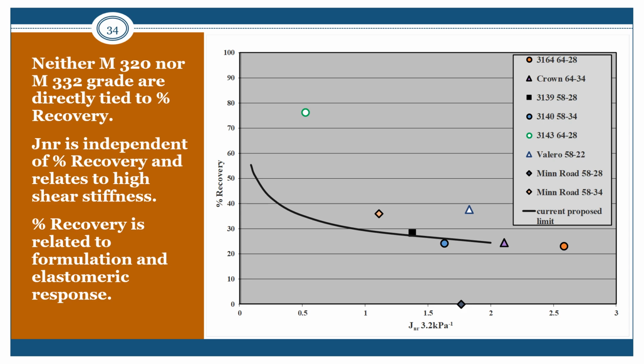As we look at this, just to show you how formulations make a big difference, you see a lot of different things here. Here is a 6428. Now we have a very lower Jnr value, very high percent recovery, for the 6428. But then when we drop down to the 6434, here we see that it has very little recovery. And the Jnr value is very, very different. So there can be a wide variety of different values here. And again, it's all based off of the base asphalt and the formulation.